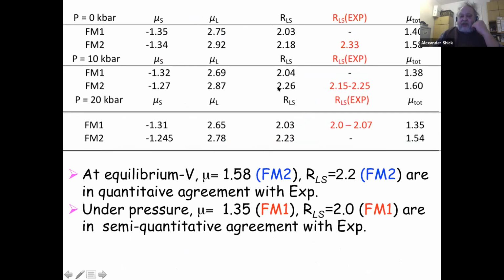Then we increase the pressure. Again, if we are in the FM2 phase, we are close to the experimental value for FM2. But then, if we increase the pressure, we can reproduce the RLS ratio according to the experimental data. So it decreases. Moreover, we also look at the total moment, which corresponds rather well for the high moment phase and for the low moment phase. Here the deviation is somewhat bigger, but we don't know why. But the RLS ratios are in good agreement with those XMCD measurements.